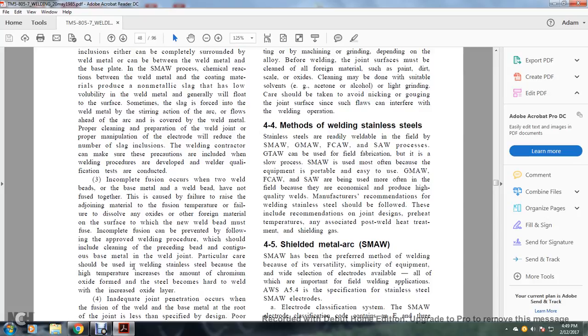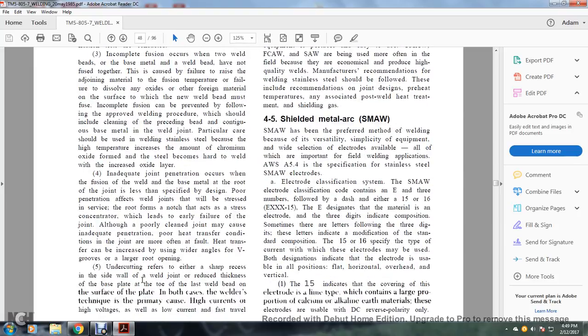Incomplete fusion can be prevented and improved with a welding procedure which should include cleaning of the preceding bead and the base metal of the welding joint. Particular care should be used when welding stainless steel because the high temperature increases the amount of chromium oxide formed on the stainless steel, which gives a hard, increased oxide layer.